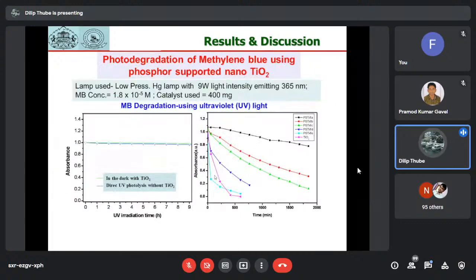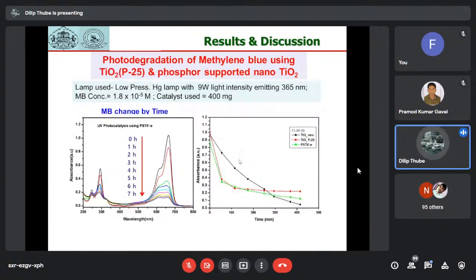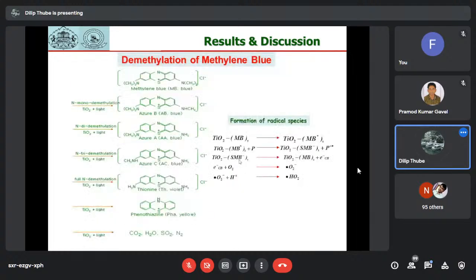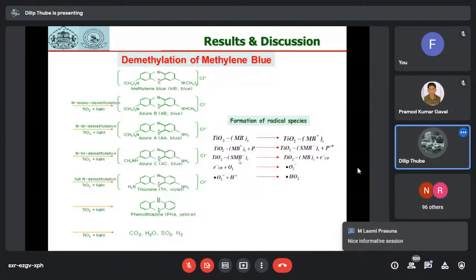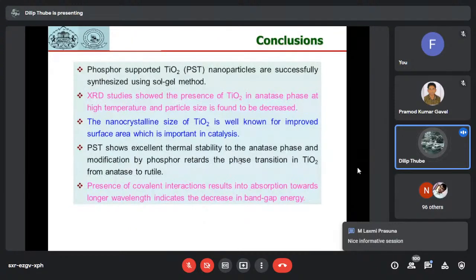This experiment is carried out in the dark as well as in the absence of TiO2 materials, and we could get very good photocatalytic degradation efficiency with one of our materials, that is PST4E as well as PST4D material. Within a very short time we observed about 87% mineralization or degradation of the material. This could be the probable mechanism for the demethylation of the methylene blue. We haven't gone into the details, but this is a probable mechanism.